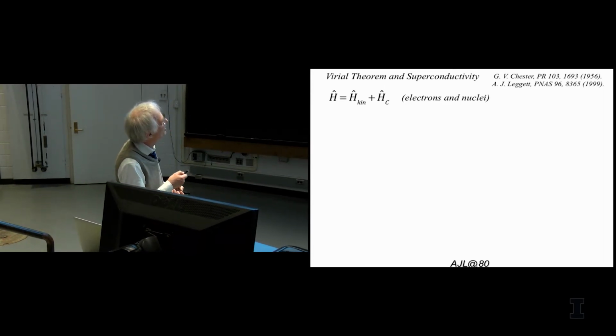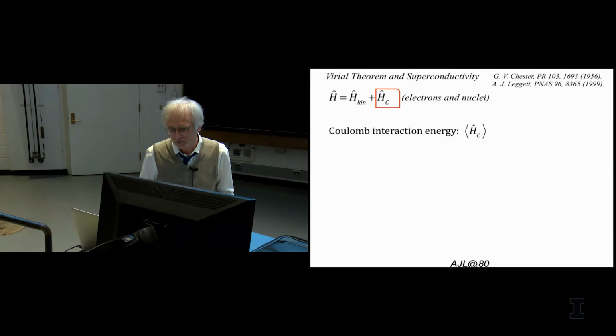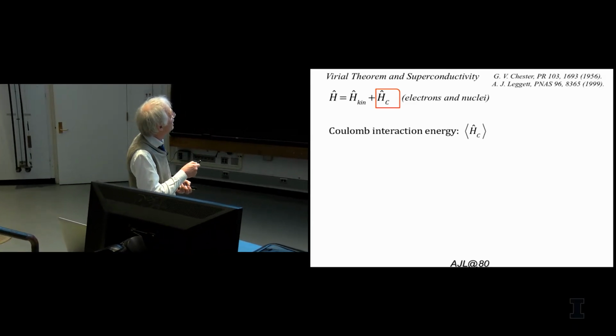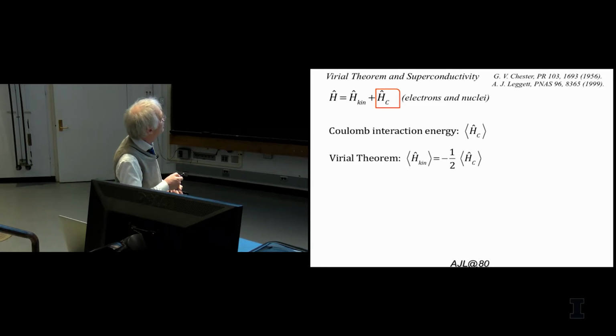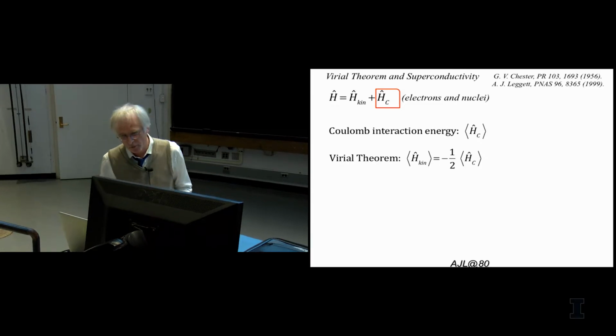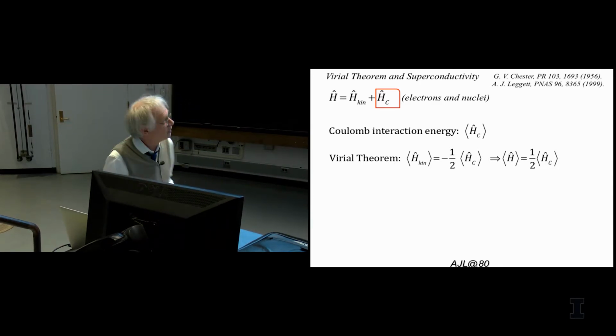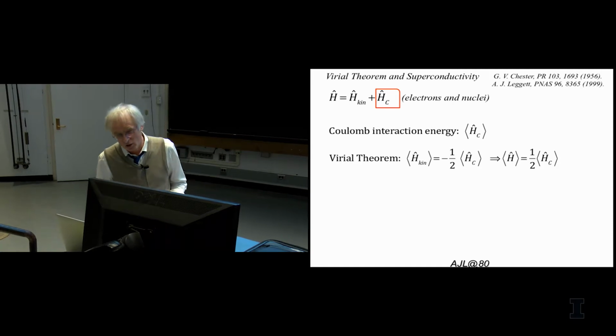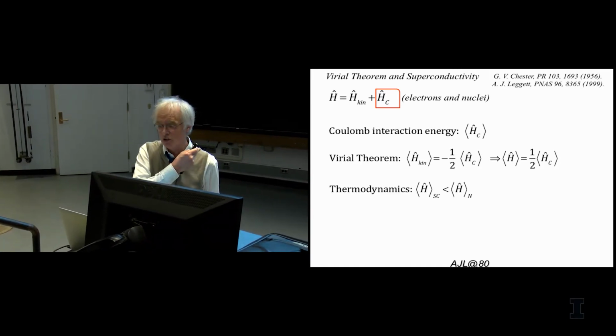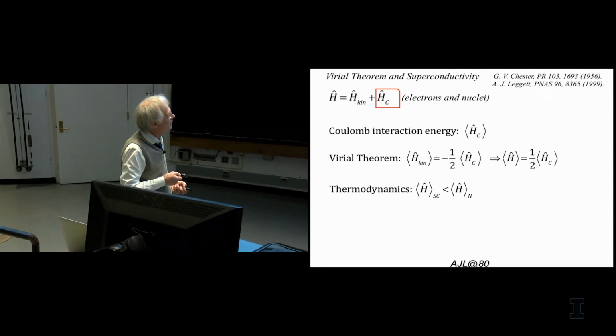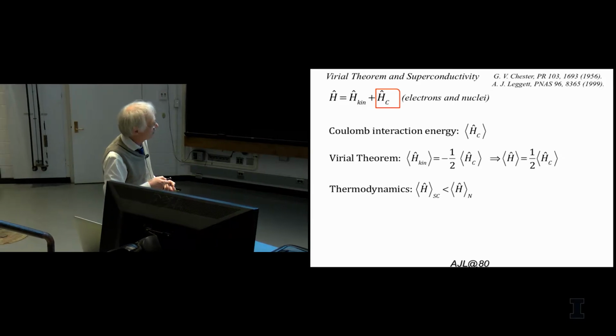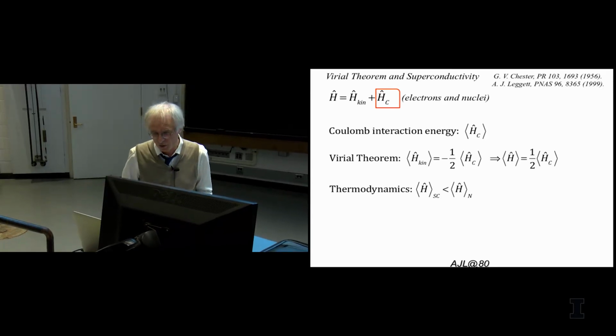And this is what Leggett actually dug up, an argument by Chester, 1956, where he said, okay, if the Hamiltonian has two terms, kinetic and Coulomb, and this is the total Hamiltonian containing everything, electrons and nuclei, then you can distinguish two terms, the Coulomb interaction energy, which is just the average of this part of the Hamiltonian, and the kinetic part. And the virial theorem will tell you that this part here has to be precisely minus half that part. Okay, so far so good. So if you take the average of the total Hamiltonian, this is going to be precisely half the Coulomb energy. Good. Now thermodynamics tells us, that's what we previously saw, this energy average, the internal energy that we saw from the specific heat experiments in the superconducting phase, is smaller than that in the normal phase. And the difference is precisely this condensation energy.